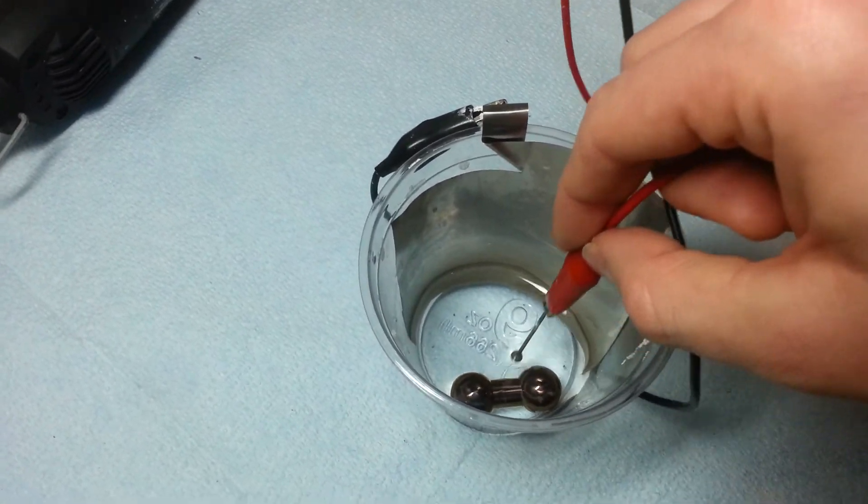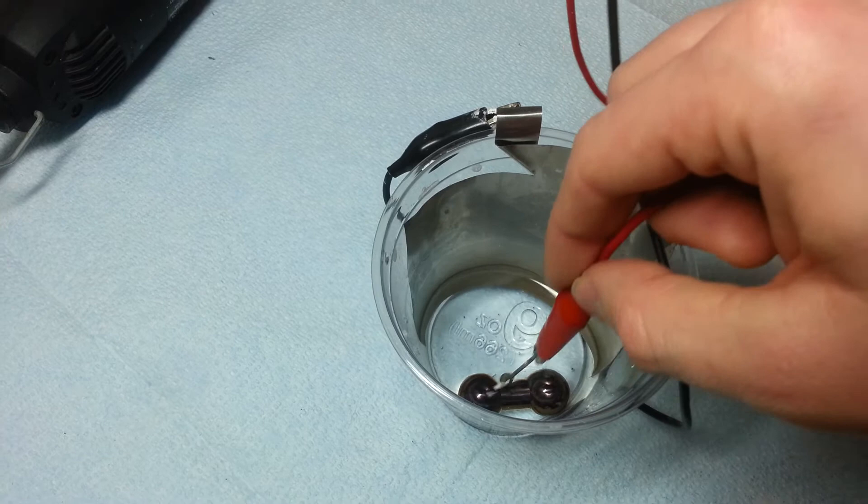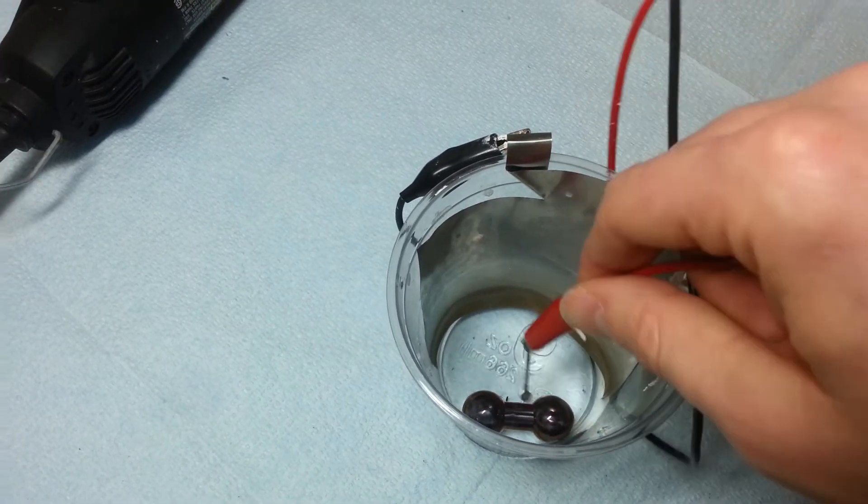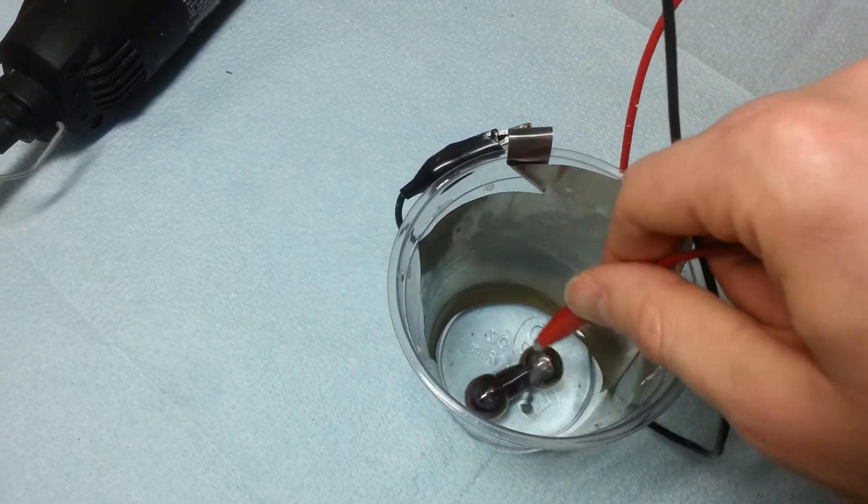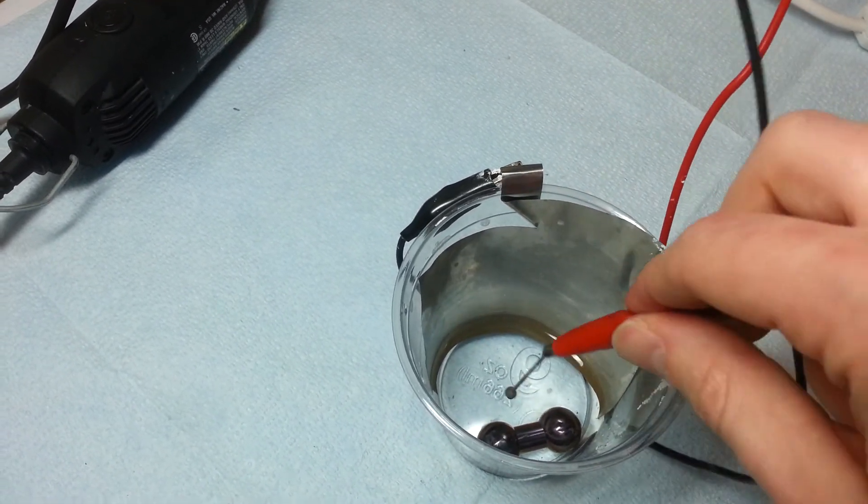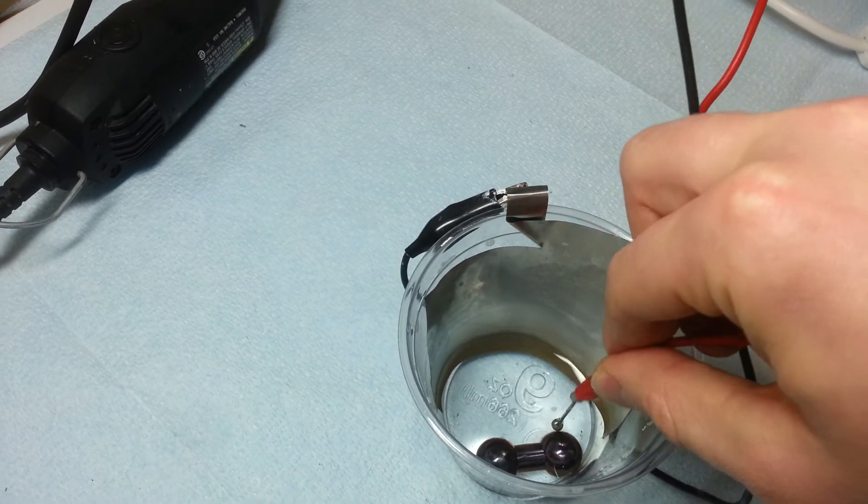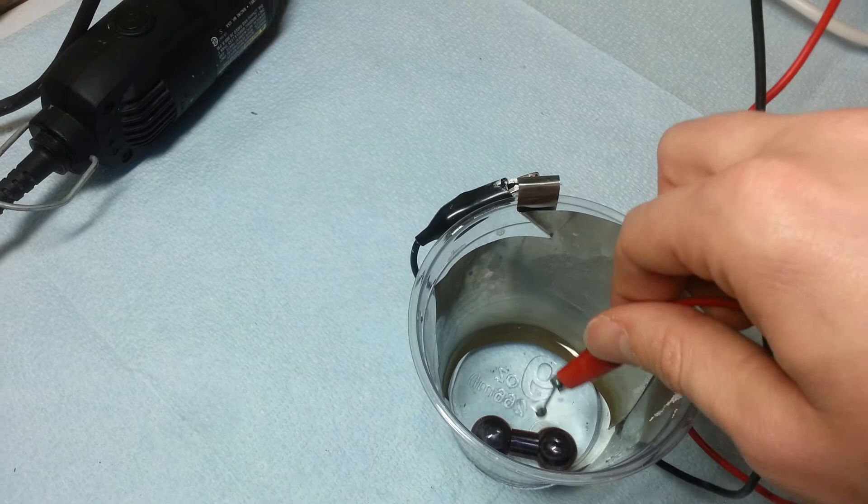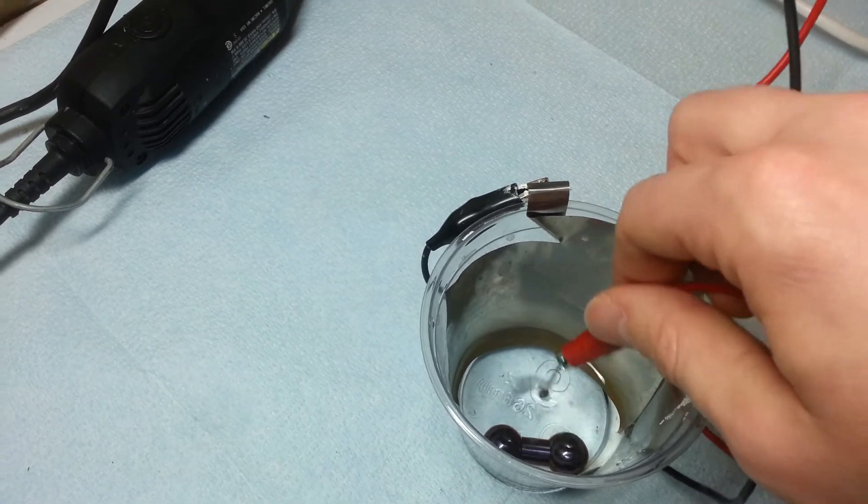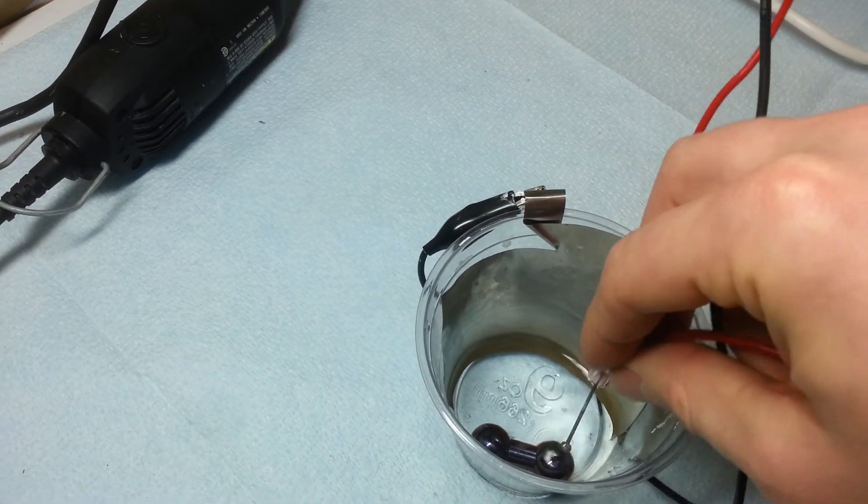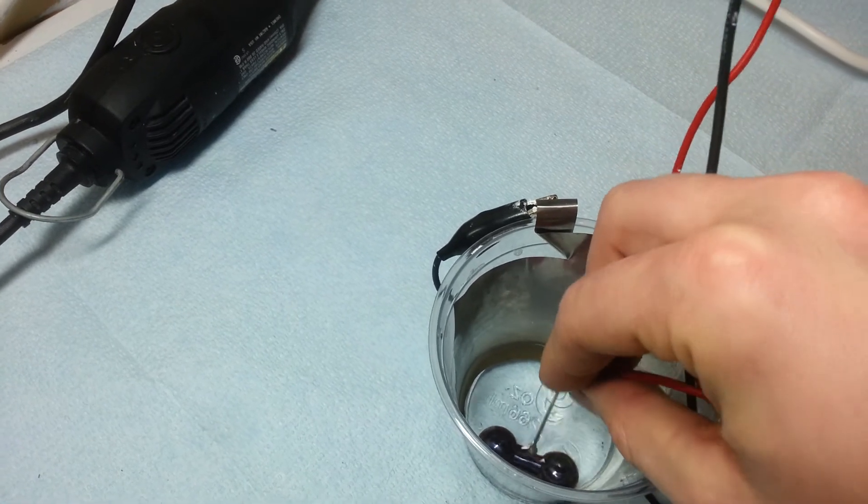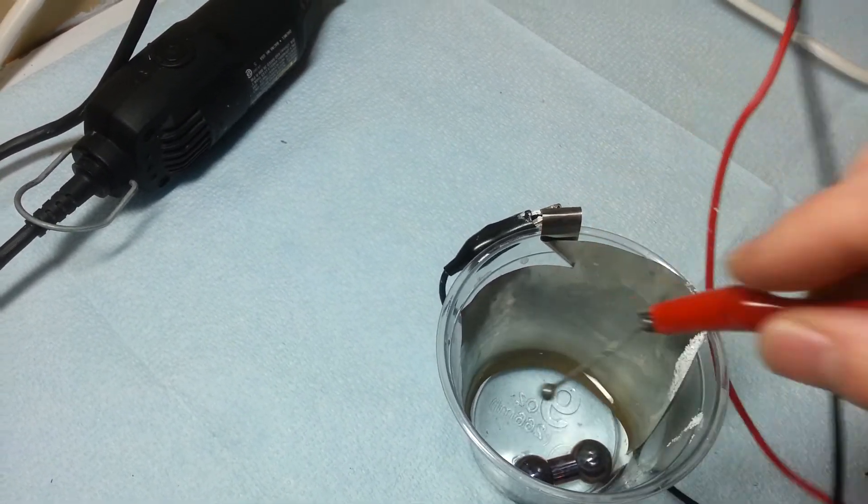You'll notice we're getting that nice coppery color. And as we come up the spectrum a little bit, we're going to get into that nice purpley color. It's important to, when you're doing this method, to tap your jewelry a lot. You're going to get little bubbles of oxygen that actually cling onto the piece of jewelry. And what happens is those oxygen bubbles will actually block the anodizing from occurring. So if you tap it and smack it,